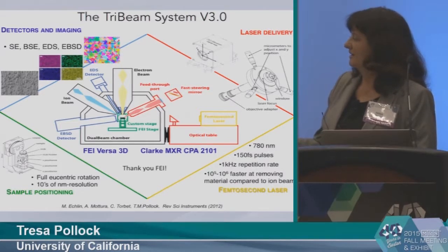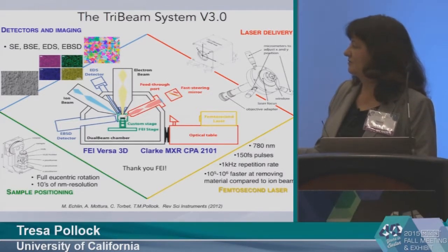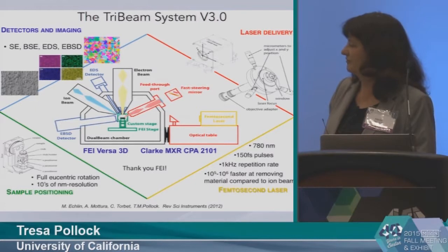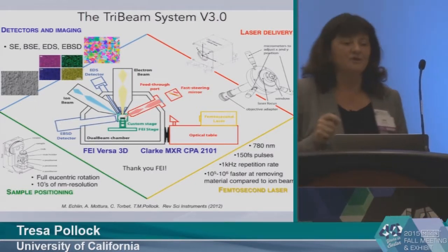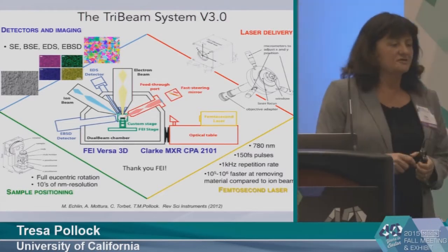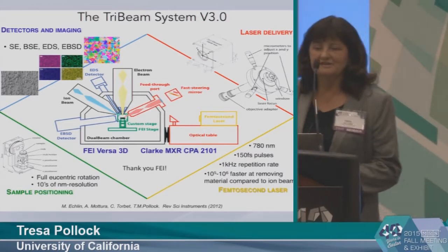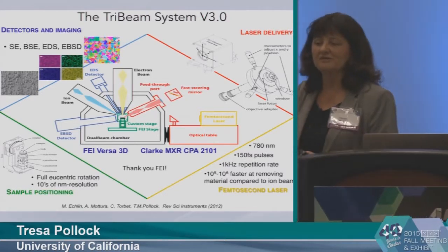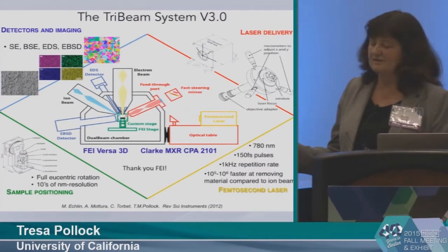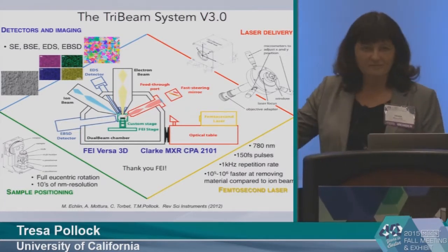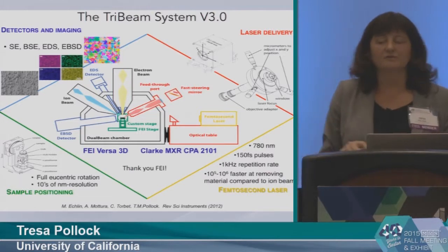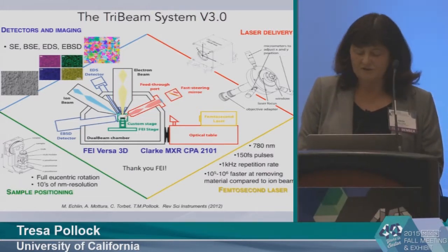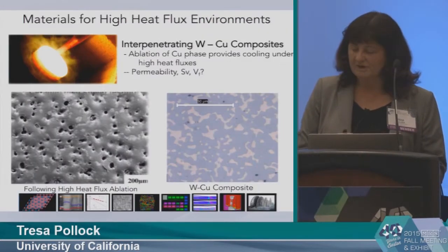So we can get crystallography, we can get chemistry, we can get structure and morphological distribution. And back to the speed issue, we can do this fast. So you've all seen focused ion beam 3D data sets. They have usually taken about 6 months to gather. This is 1,000,000 times faster because the femtosecond laser can remove material layer by layer without any significant collateral damage.